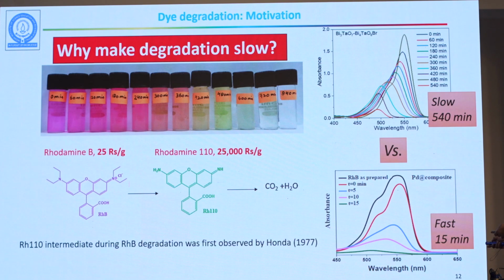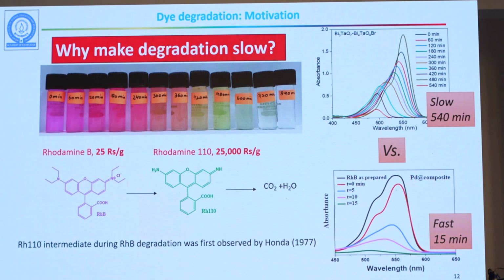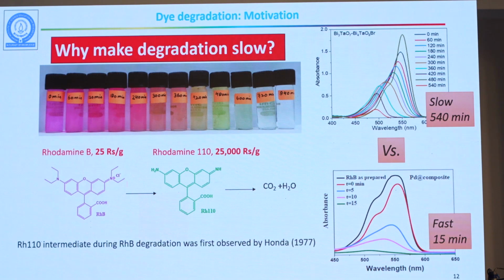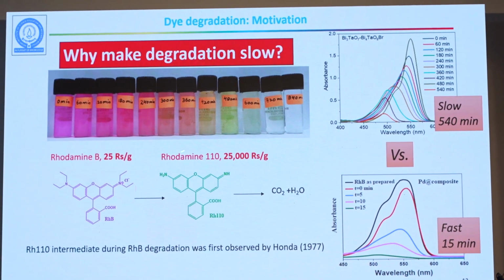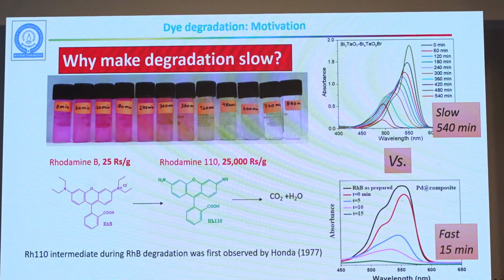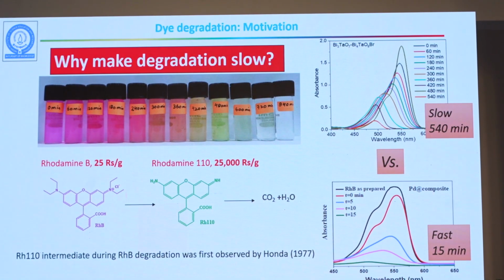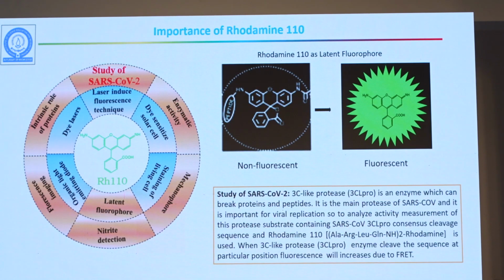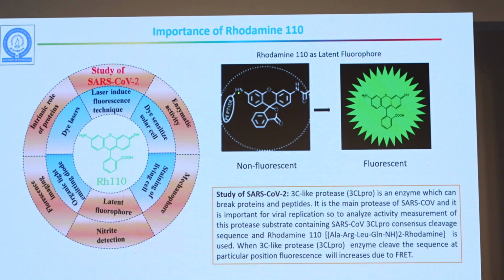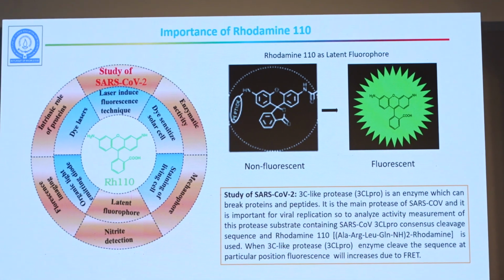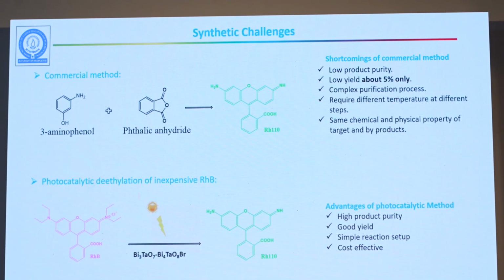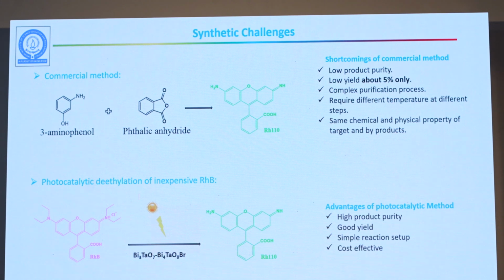So what you essentially see is that if you make this process slower, you start seeing what happens in between. And if you see what happens in between, you end up getting something which is very, very expensive. So if you can extract it, the dye gets converted to something very useful. So I explained what is profluorophore. When it forms these amide bonds, the molecule twists and it is no more fluorescent. So it's a probe. So normal synthesis of rhodamine 110 is expensive again because it is very reactive. You get roughly about only 5% yield. The rest of them are byproducts. So you have to clean them. So it becomes very expensive.